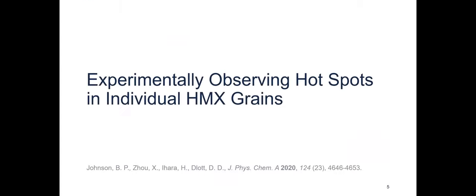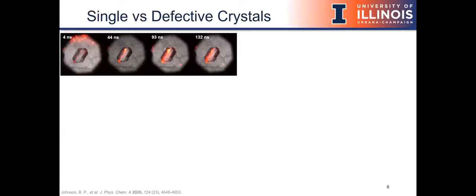To move on to the last detector, this is an optical pyrometer that has been described multiple times by the Dlott group. We can produce and calculate temperature transients with down to two nanosecond time resolution using gray body method techniques. With that, we are now ready to talk about results. I'm going to briefly highlight three studies today. I like to start with this first study that we published early last year, where we were really aiming to establish this technique and these methods. For this study, we really wanted to create a baseline understanding for what this model system is doing.